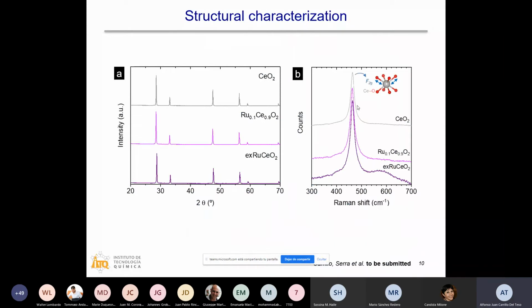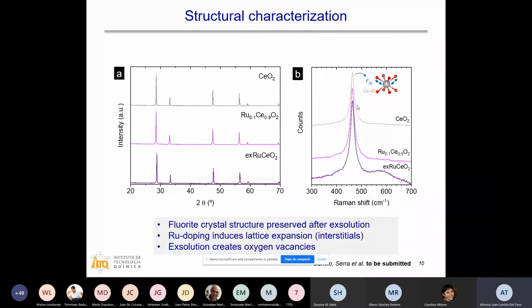We analyzed these materials by XRD, and we observe that all of them preserve the fluorite structure, obviously with some structural differences that we also checked by Raman spectroscopy. As Professor Haile suggested to our previous speaker, this is a very interesting technique to study cerium oxides. We observed that by ruthenium doping, there is a lattice expansion, and this was quite intriguing at the beginning. We think that the reason is that the ruthenium goes to the interstitials. And after exsolution, since we are doing this treatment in a reductive atmosphere, we observe the creation of oxygen vacancies that can be seen in the Raman spectra at around 550, 600 wave numbers.